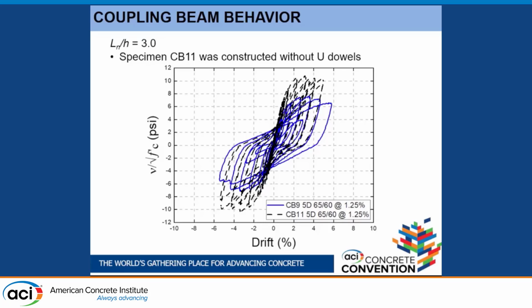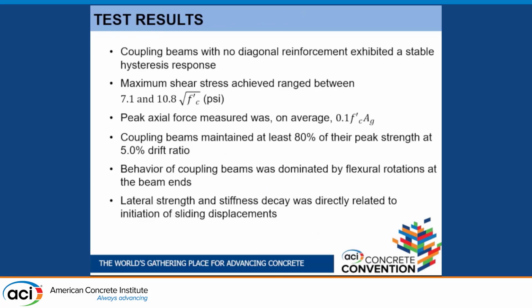That means we can simplify the reinforcement, remove the dowels, and still achieve good performance. Summary of the test results: we can get a fairly stable hysteresis response at high shear stresses for all the tests that range between 7.1 and 10.8 root of F prime C.